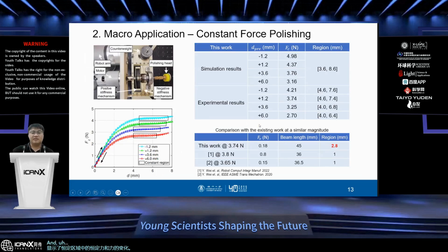An experimental study was carried out to measure the actual performance. Compared with the simulation result, the experimental result of the magnitude and range of the constant force region have both decreased. It also showed that the measured constant force regions with various preloading displacements are inconsistent. The difference may be induced by the manufacturing error, assembly error, and measurement error.